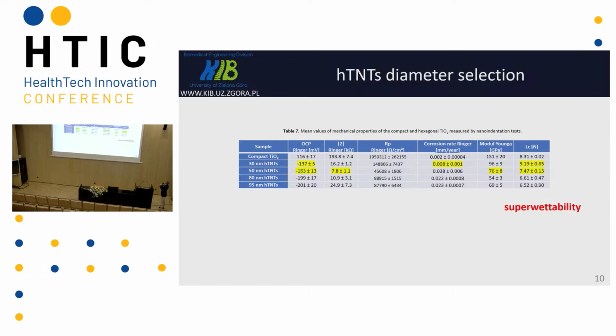I haven't shown you the result of the wettability measurement, but generally all of these structures, never mind if we talk about the very small or very high diameter, revealed super wettability. The drop put onto the surface immediately disappeared. So we decided to use in our future research the HTNTs with diameters of 50 nanometers due to this parameter.